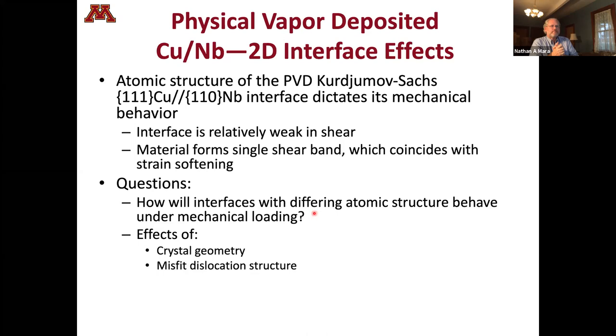Yeah, Nate, I got a question on this. Is there a modulus limit in terms of the metals absorbing these defects at the interface, or is it just the crystalline packing? Oh, good question. So the local modulus and elastic properties of the material dictate, to a large extent, the motion of these dislocations, because you're making and breaking bonds locally. And so the local strain field around that dislocation is key to what that dislocation sees around it.